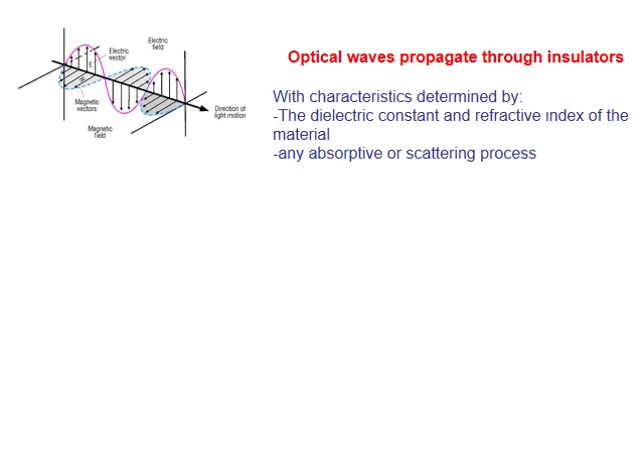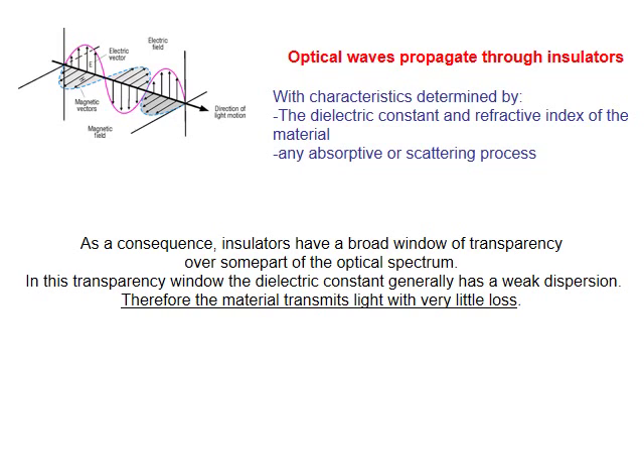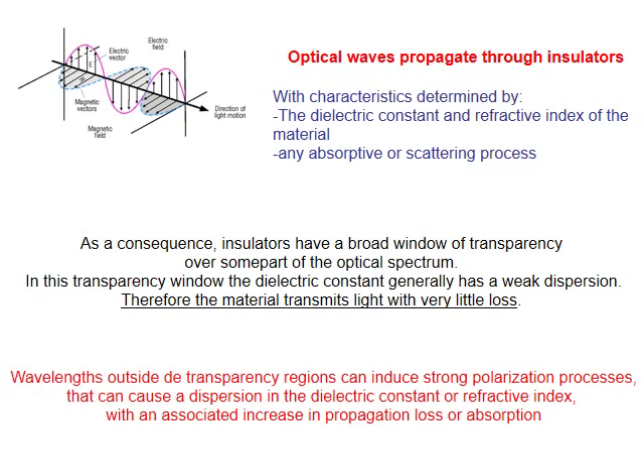Optical waves propagate through insulators and do so with some characteristics determined by the dielectric constant and refractive index of the material, and by any absorptive or scattering process. As a result, insulators have a broad window of transparency over some part of the optical spectrum. In this transparency window, the dielectric constant generally has a weak dispersion, therefore the material transmits light with very little loss. Wavelength outside the transparency region can induce strong polarization processes that cause a dispersion in the dielectric constant or refractive index, with an associated increase in propagation loss or absorption.